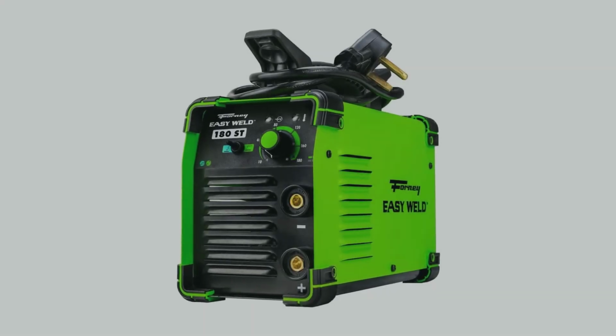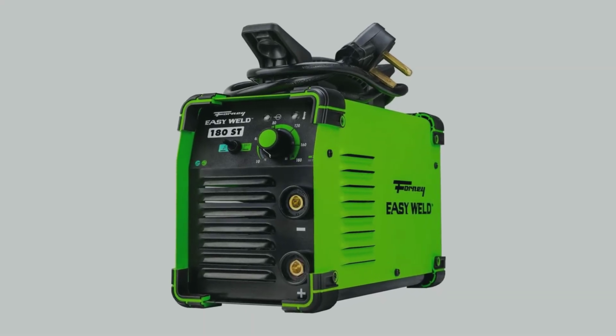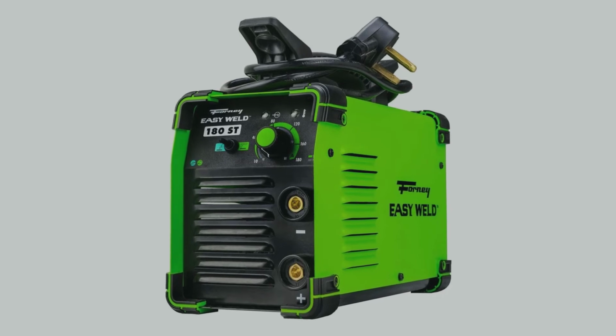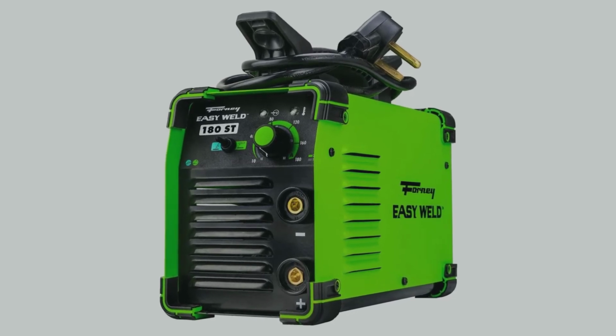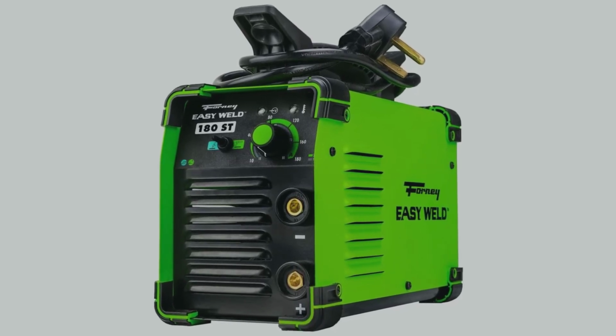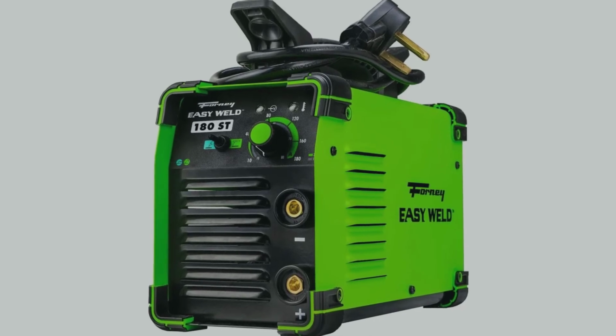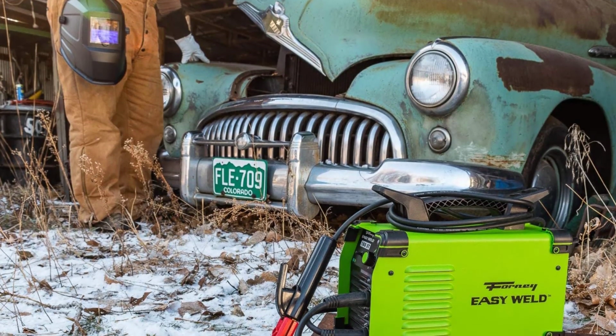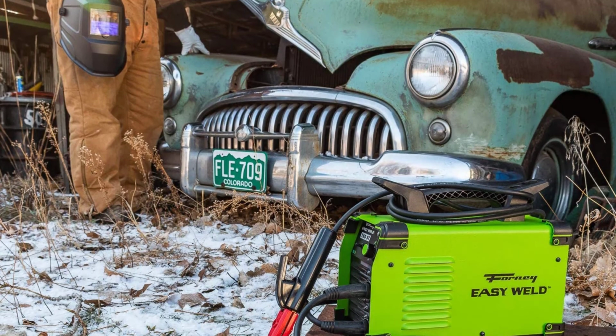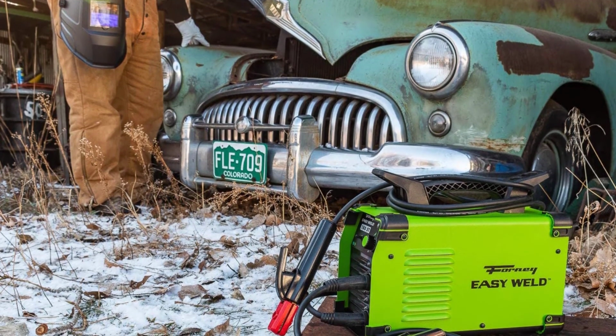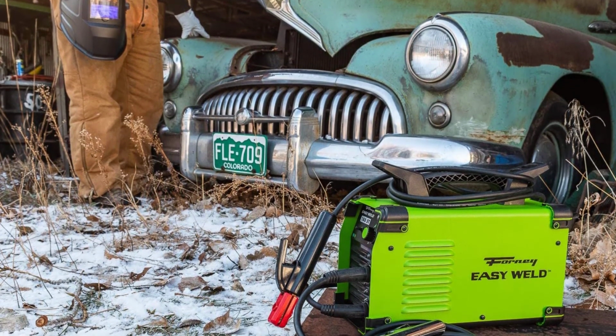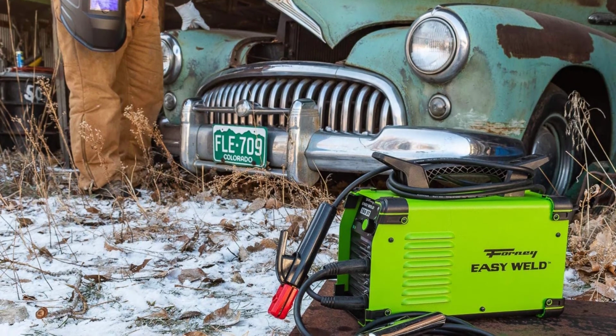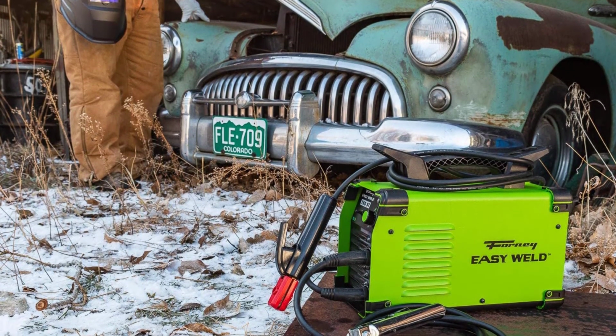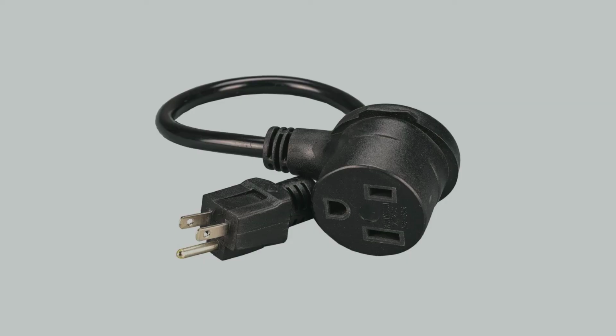This is a great stick welder from Forney that's the big brother to the 100 ST. It can run almost standard electrodes pretty well, and can run 1/8 6010 and 7018 on 120V, but for best performance, you'll need to hook up to 220 volts. It will weld up to 1/2 inch mild steel on 230V, and 1/4 inch mild steel on 120 volts. The arc strikes well, and it has easy start technology to help minimize electrode sticking.